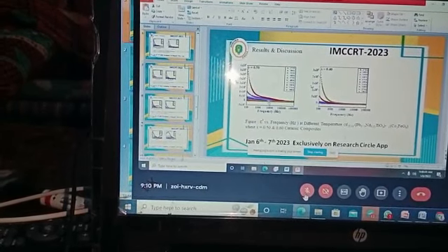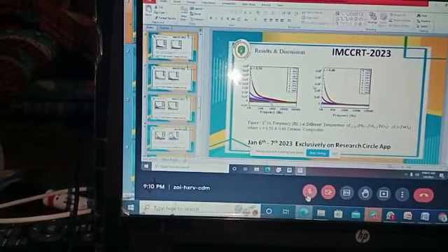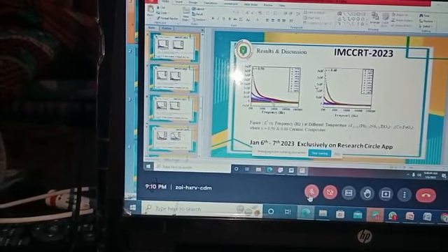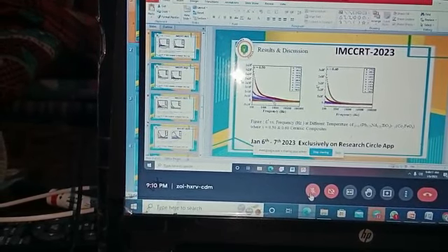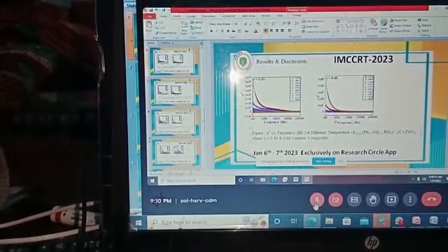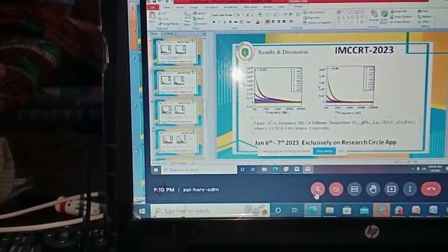From the graph of the real part of dielectric, we see that when we increase the magnetic component, the dielectric constant decreases in comparison to the composition in which the lanthanum ferroelectric component is more.